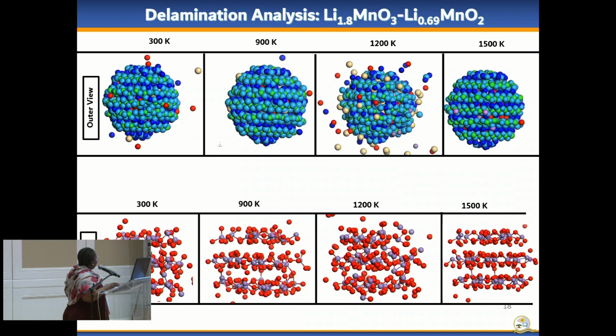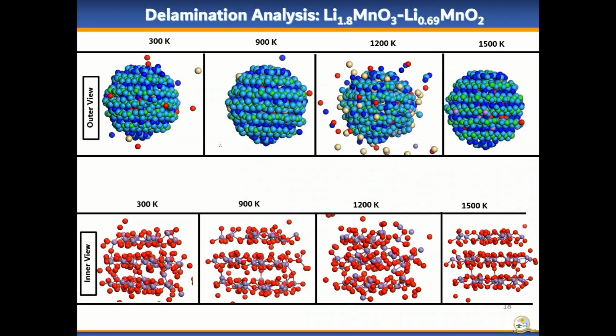Basically what we saw is that the shell material remains intact, and the atoms come out from the core, go back at 900, come out again at 1.2, then it looks more stable again here. When we looked at the composition of the core alone, this is the Li2MnO3. In this case it will be Li1.8, because we are charging it. Here we have a structure that looks ordered. These are the manganese and oxygen layers, and this is normally where the lithiums are, so we removed them for clarity.